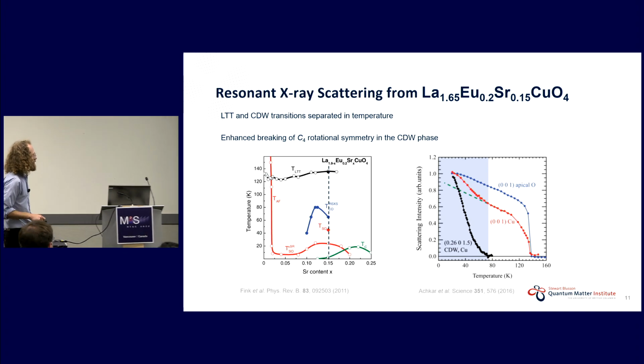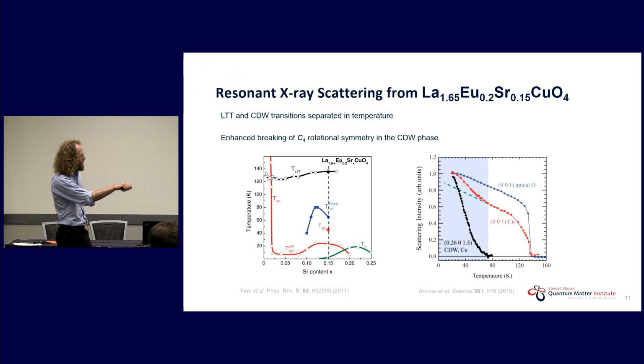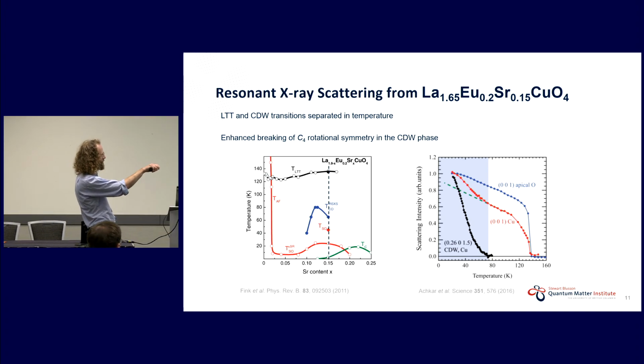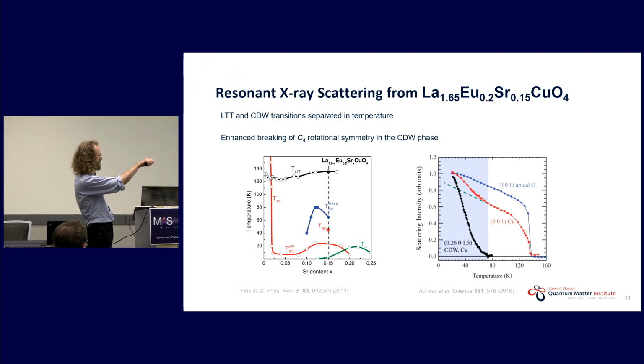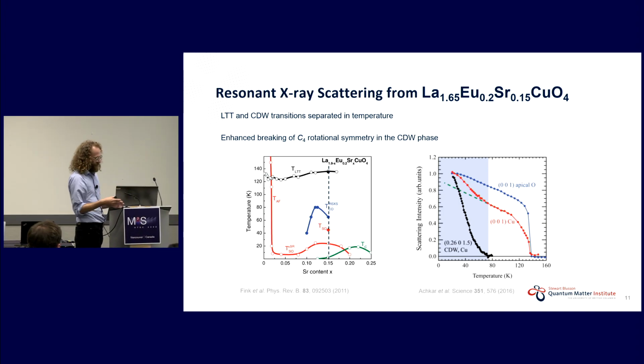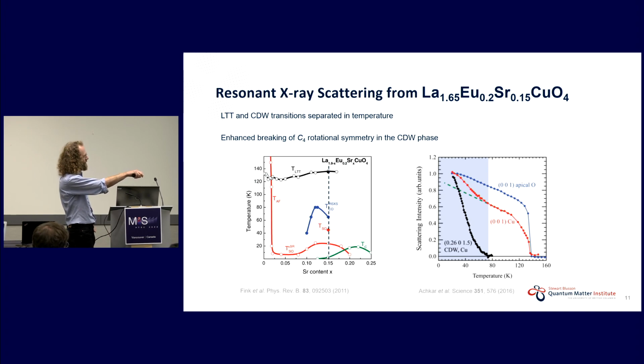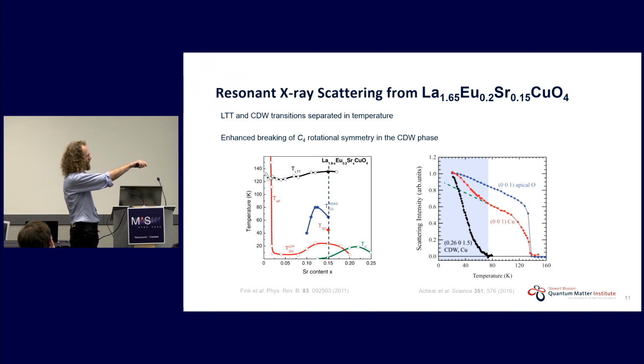First, just in equilibrium to show you how this looks, we choose as our study candidate LESCO, and the reason we do this is because the LTT distortion is strongly separated in temperature from the charge order. Okay, so if we now go to this 001 peak, which shows us this rotational symmetry breaking, at the apical oxygen, we can see just an onset at the LTT temperature, 130, okay, and an order parameter like onset.